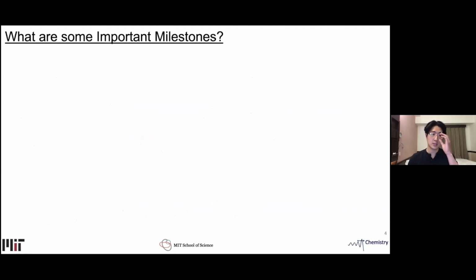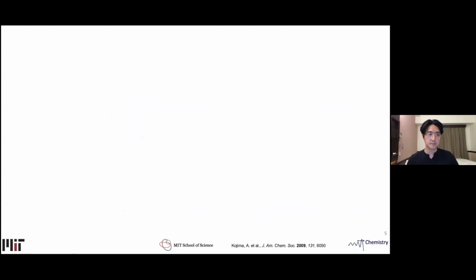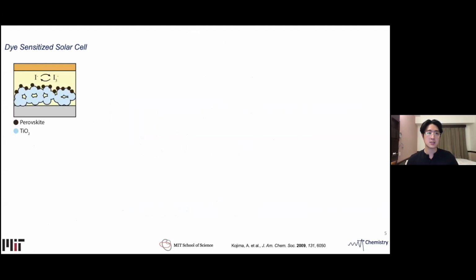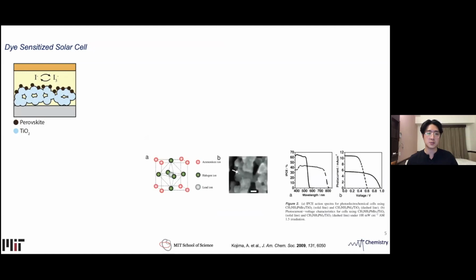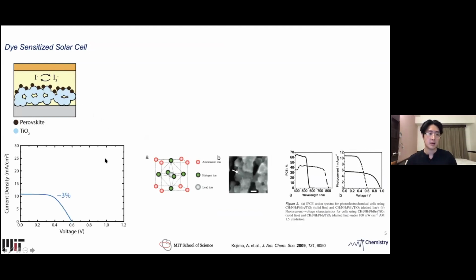Here, I want to introduce some important milestones in the perovskite solar cell community. First, the concept of using perovskite as a light harvesting material was introduced in 2009, when researchers grew a tiny perovskite crystallite onto a titanium dioxide scaffold. This was prepared to be used as a dye-sensitized solar cell. On the left, I'm showing a JV curve from this work, and they report an efficiency of around 3%.